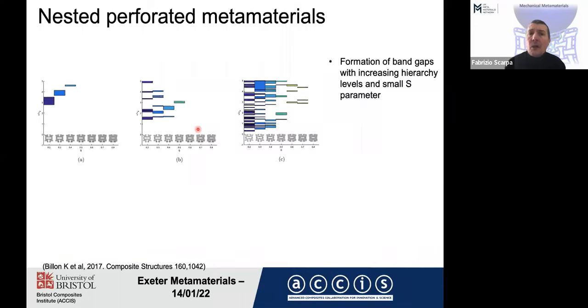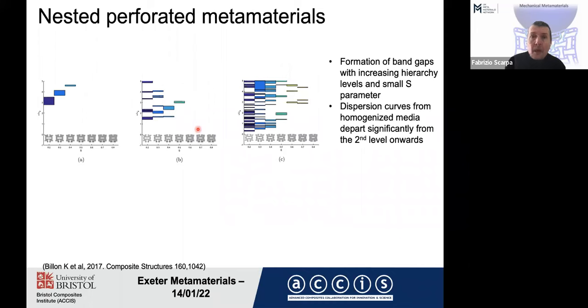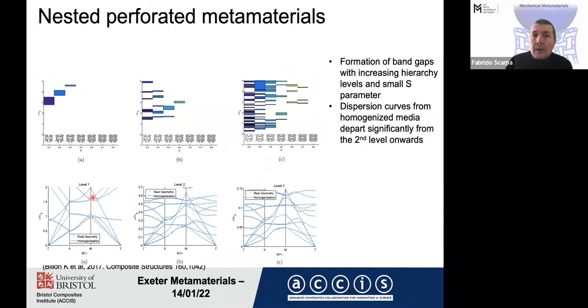And this is also seen quite clearly when you try to map the amplitude and the number of band gaps versus the different aspect ratios of the perforation and also the interspace distance. There is something that I need to warn you about. You cannot simply reproduce this type of dynamic behavior by asymptotic homogenization. If you try to calculate the dispersion curves using the Christoffel equation, you can still obtain a fairly decent match between high fidelity Bloch wave and homogenized dispersion for the first level. But as soon as you increase the order of the nesting, the match is not there anymore.